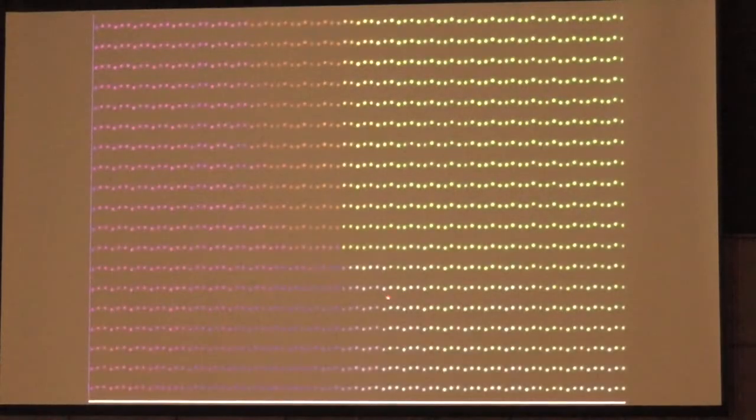So in this case, we were able to see this ferroelectric vortex. And in erbium manganite, this atomic resolution STEM allowed us to measure the local order parameter changes, both going around these topological defects through vortices and domain walls, and also over the overall crystal to see what the measurement of the local energy landscape was.